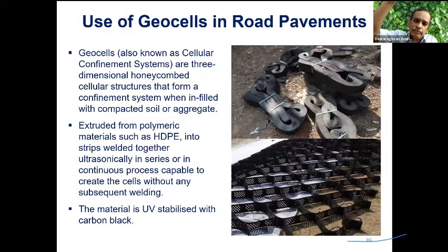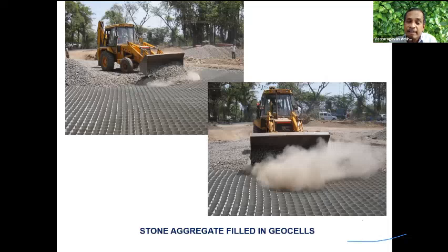Instead of having 250 millimeter for granular subbase, you can bring down thickness to 100 millimeter, maximum 150 millimeter. It enables the water to get out. Confinement is there. Significant reduction in the thickness, improved performance, and lower life cycle cost. It's time that we look at the new materials.